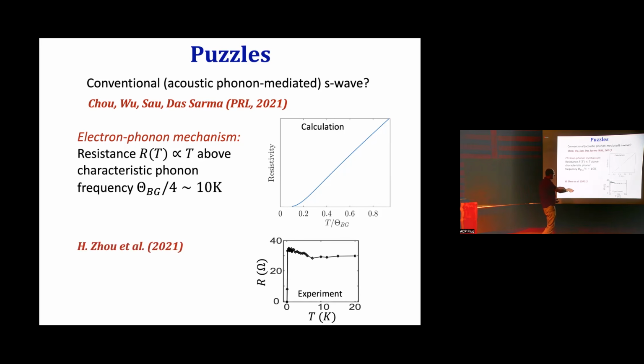And this is what the experiment shows. This is in one of these superconducting phases. This is the resistance as a function of temperature. You see here the superconducting transition. But above the superconducting transition, it really looks nothing like that. It's to zeroth order temperature independent, and if anything, it actually goes a little bit down with raising temperature.